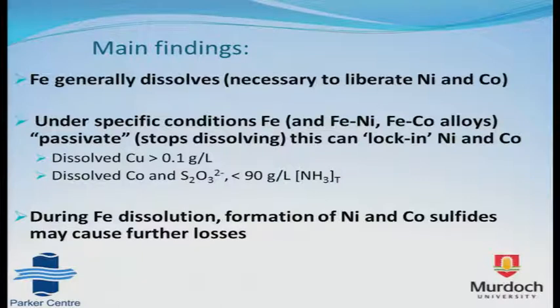However, there are specific solutions, specific conditions in which the iron, and similarly iron nickel and iron cobalt alloys, are passivated, which means they stop dissolving, and therefore, if it is an alloy, it can lock in the nickel and the cobalt. The specific conditions in which this has been found to take place is in the presence of copper, even at very low 0.1 gram per litre amounts, or in the presence of both cobalt and thiosulfate ions, though this does take place at a slightly lower total ammonia concentration to those employed at current plants generally.